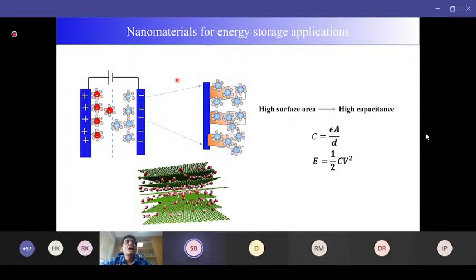Now the question is how to increase the energy storage performance in a supercapacitor. What should be the material characteristics used in the two electrodes so that we can boost the energy storage metric? Here is one schematic example: instead of a thin plate, if you use a porous electrode with thin sheets of some materials, the adsorption of charges not only happens on the two-dimensional surface of the electrode, but on each and every surface of these porous structures, so that you can increase the energy storage to a high extent.